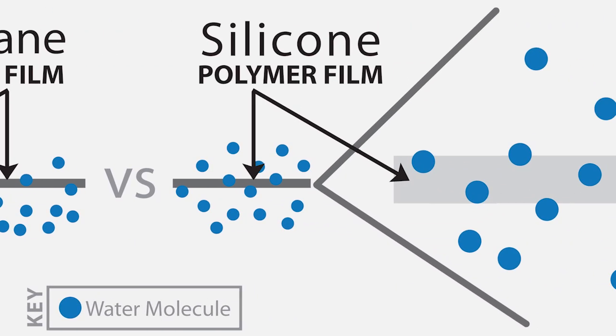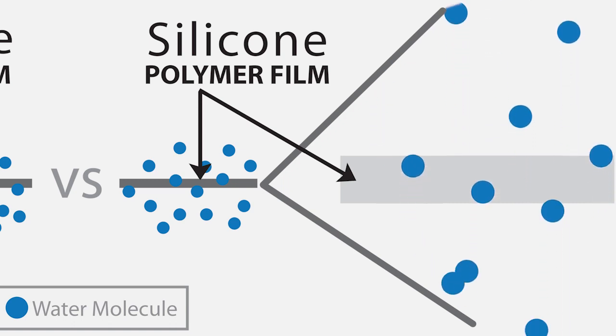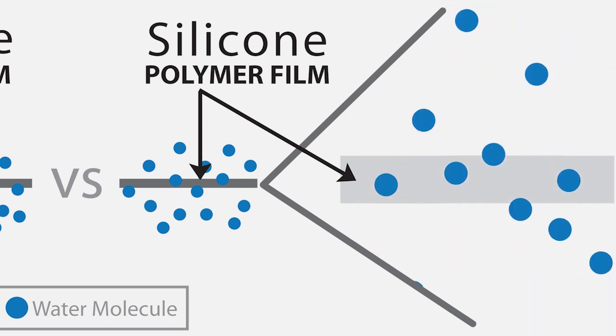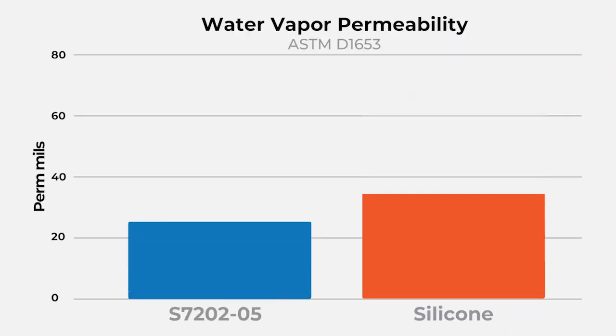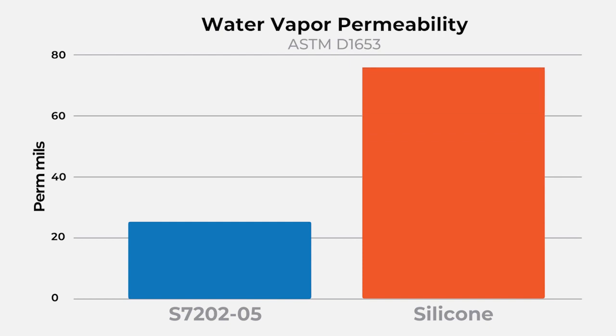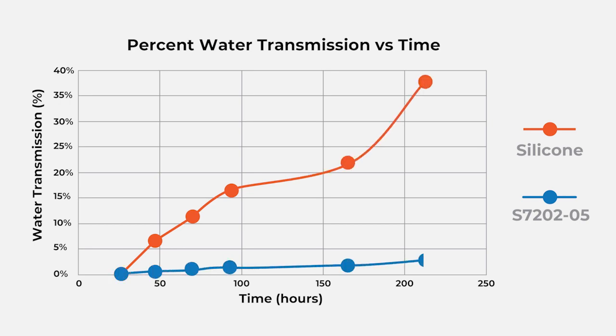Because polymers will have different water vapor permeability, varying amounts of water will be drawn out of the cup as illustrated in this graphic. This is a side-by-side comparison of S7202-05 and an industry-leading silicone potting compound. This shows how different polymers will have different water vapor permeability. As the exterior of a sensor is exposed to humidity, it begins to accumulate in the sensor. This causes degradation of the electrical performance of the circuit until it fails. Since humidity is ubiquitous, it is essential to utilize potting compounds for the best protection from water circuit failures.